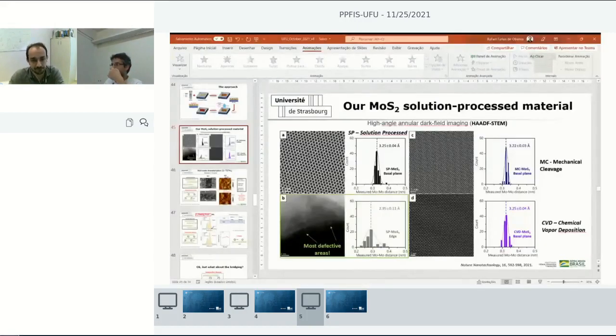So I was thinking that the connection was not at the edge but at the basal plane. I wonder if it's possible to increase the distance between planes, like a polarization of the system, by incorporation of molecules with larger length, so you can increase the vertical distance between the layers. But it does not occur because the connection occurs at the edge sides.